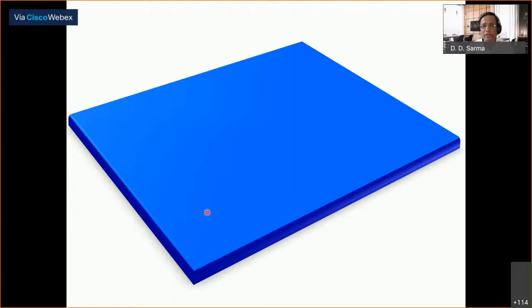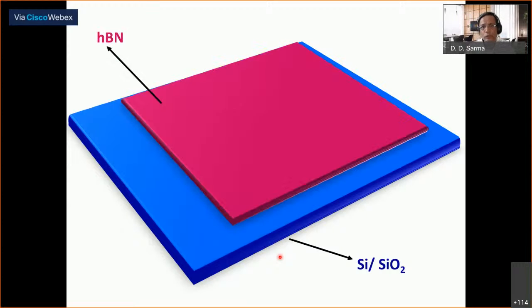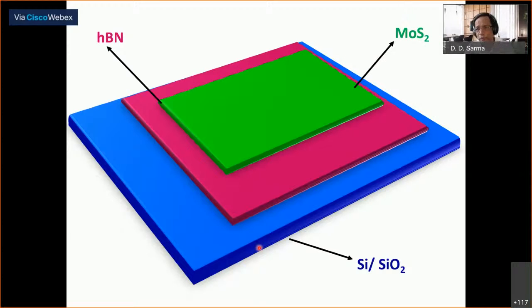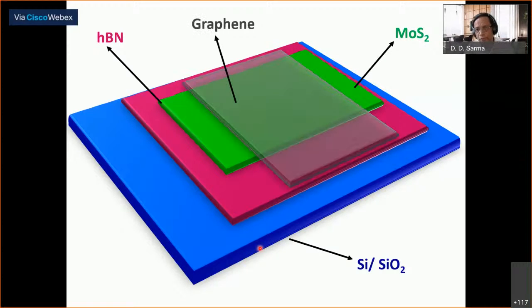What I'm going to talk about is a heterostructure using MoS2. So you take a wafer, which is your substrate on which you're making this heterostructure, and you put an hBN, hexagonal boron nitride, to separate out any coupling to the silicon, silicon dioxide substrate. And then you put your MoS2 on top of it, and then you make a heterostructure with a graphene on top. And you want to understand, because there are a lot of very interesting claims on this system.